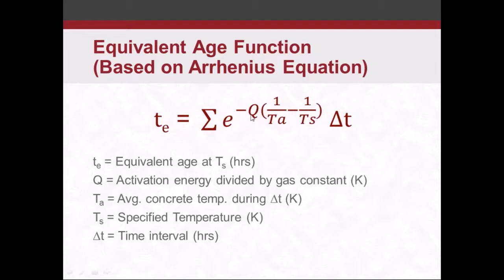The ASTM tells you how to get that activation energy, very similar to, or also using, 2x2-inch cubes. T sub A, same thing here: average temperature during your time. This is in Kelvin. This activation energy is also in Kelvin. Specified temperature T sub S, that's your laboratory curing temperature, right? Again, that's in Kelvin. And then your time interval is in hours.